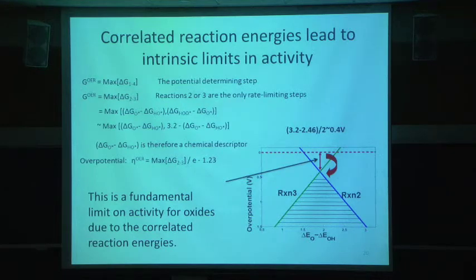It suggests that with a single site oxide electrocatalyst, you cannot get arbitrarily close to a 0 millivolt overpotential. It implies there's a kinetic limitation on the overall activity of an oxygen evolution catalyst because those steps are correlated with each other. If they weren't correlated, we wouldn't have this problem. You could independently move off of them. But the correlations lead to this kind of a volcano.